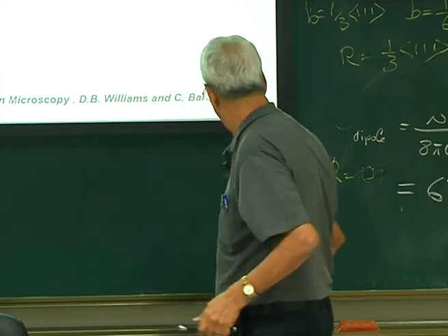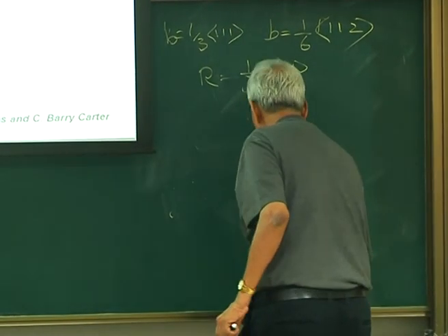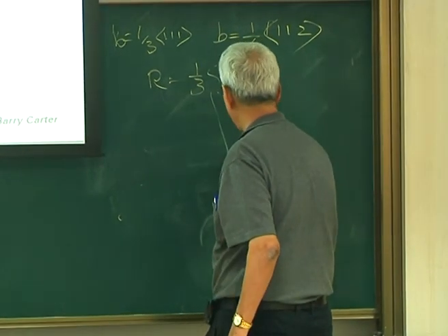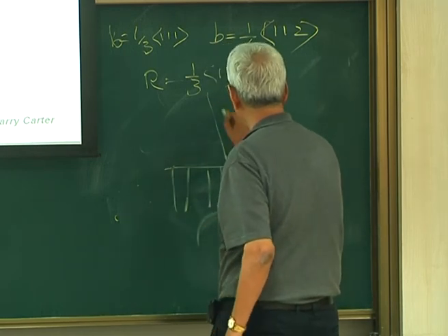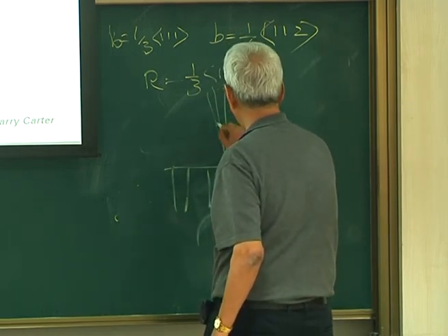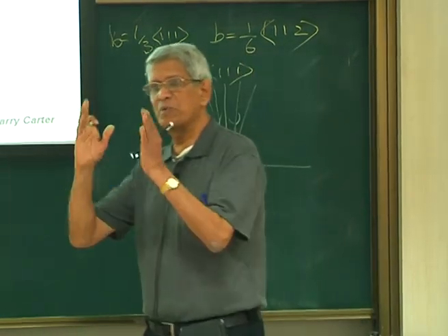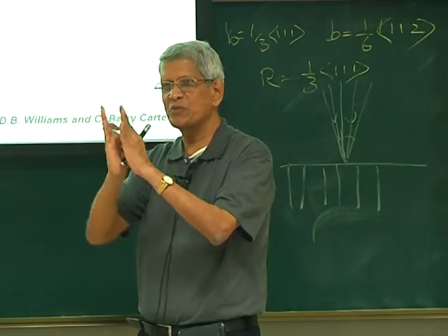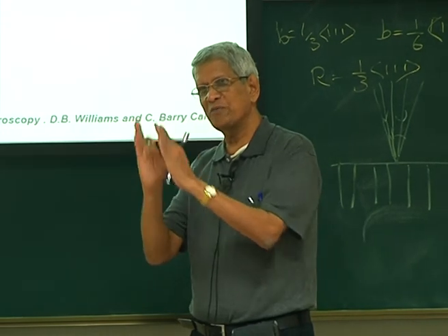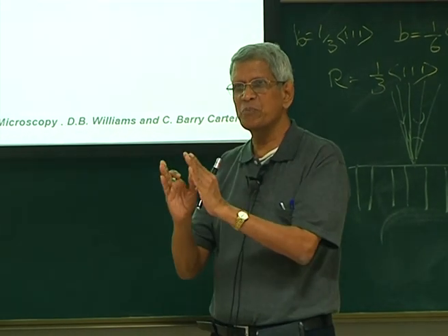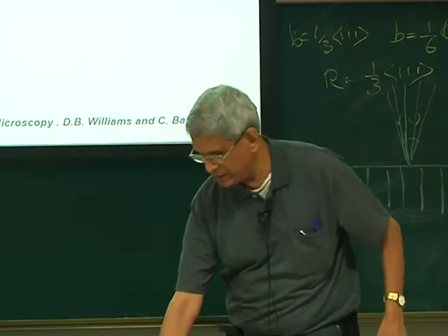That means that it is essentially having a beam converged like this, falling onto a sample. That means that I can assume this to be equal to so many directions within this range of angle. So, beams parallel to each other with various orientations are falling onto that sample. Some particular orientation will exactly satisfy, others we can say S is varying, the deviation is varying. That is precisely what happens in this case.